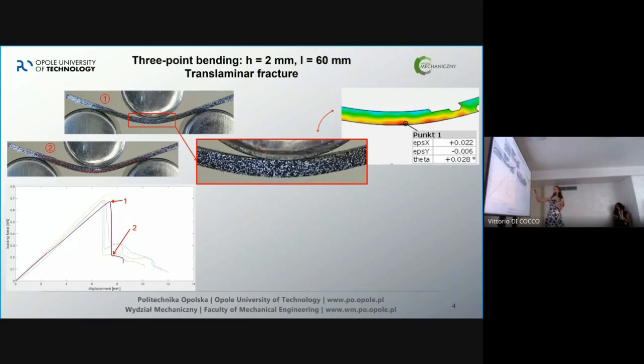0.022. So it was the value when this crack, when the fibers crack, actually, because fibers are the thing that keeps it together. So when the fibers crack, then the material cracks. And just in the next step, because it's like 30 milliseconds after, there was a crack already, and we could see that there are straight lines in here, and just this part was an arc. So we knew that the material can no longer be used.